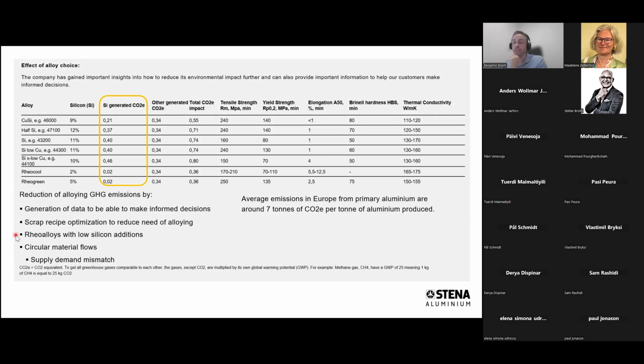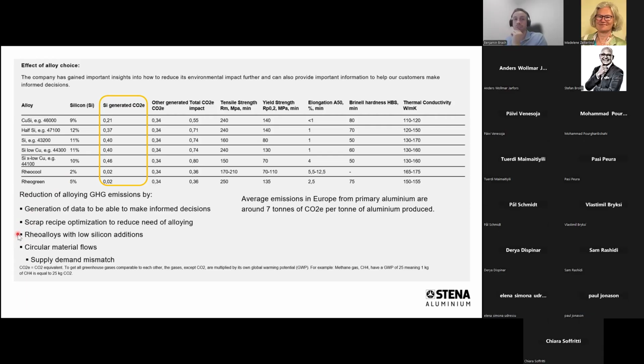As I mentioned, Rheoalloys with low silicon additions. So these are alloys with, as it says here, 2 or 5% silicon final content. So it's very low, meaning that you don't have to add basically anything. It's very low amounts of additions. So that also means low total emissions.